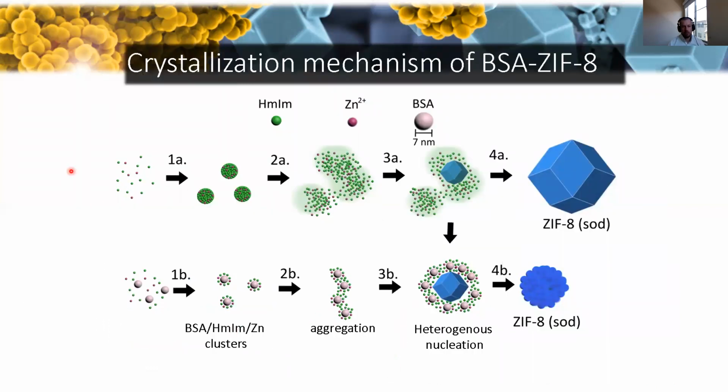So just to summarize, what we found is that we have this ZIF-8 mechanism by itself that involves the formation of these amorphous precursors. They dissolve to form this amorphous, more liquid-like material, and that's where these ZIF-8 crystals grow out of. In the presence of the biomolecule, we believe this process is exactly the same, but the biomolecule interacts with its own set of precursors in solution to form this aggregated network phase, which then undergoes a solid state transformation on the surface of these growing crystals.